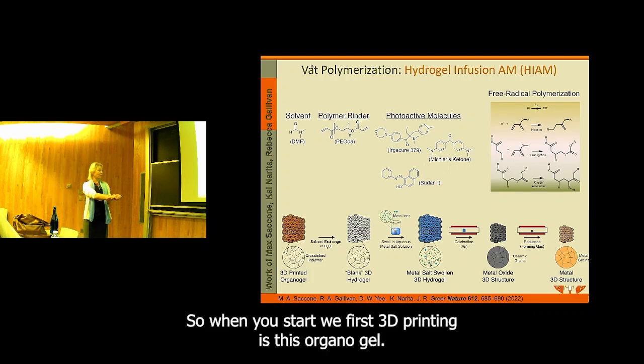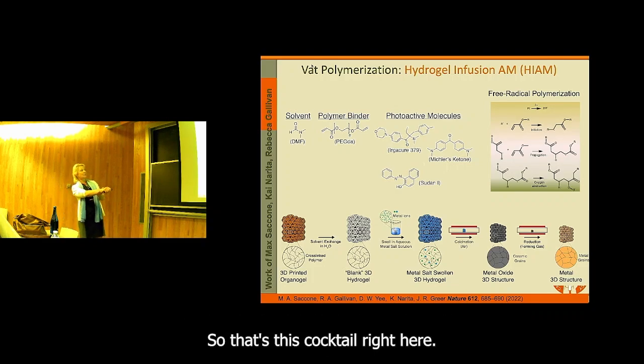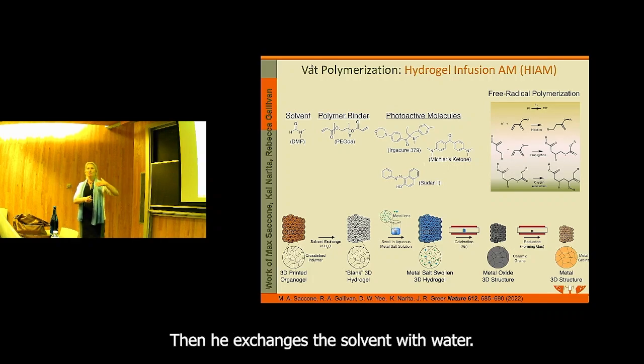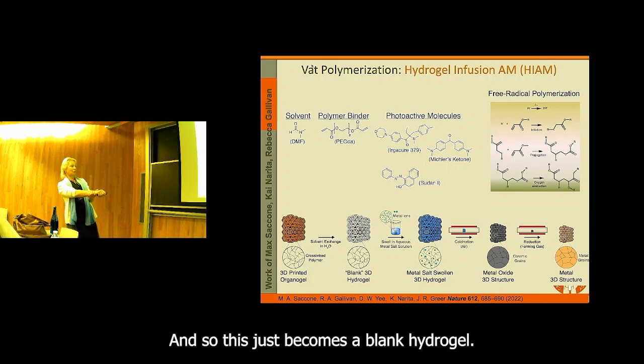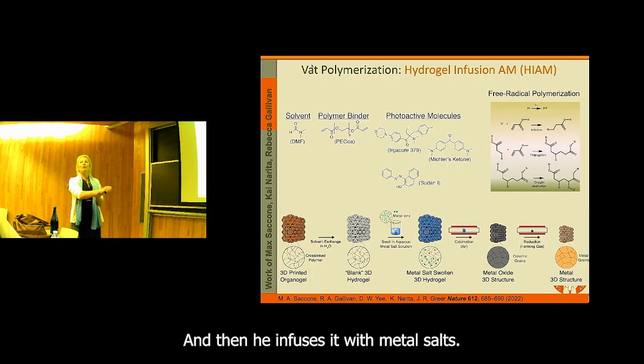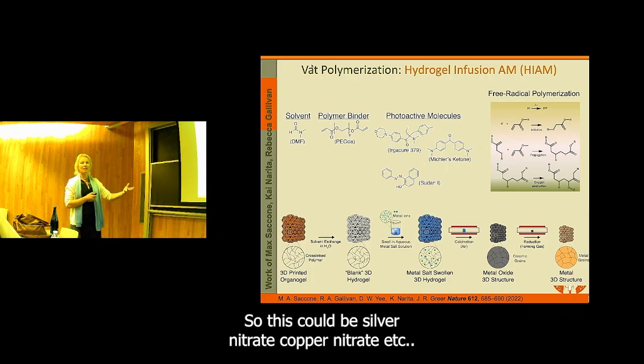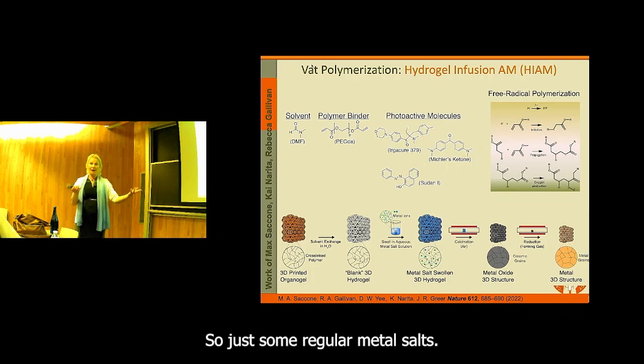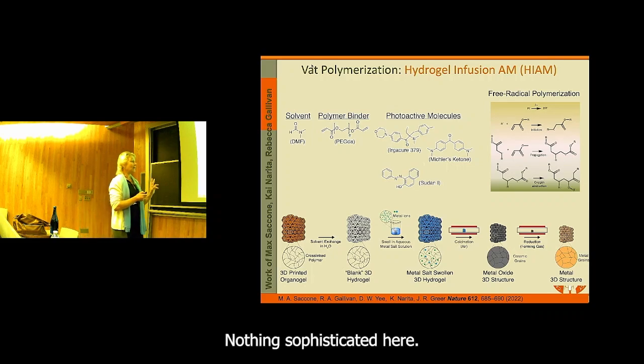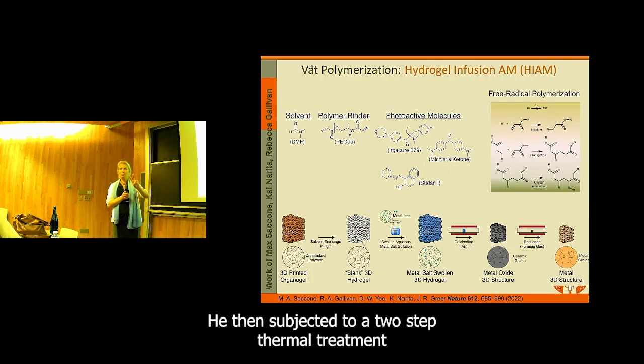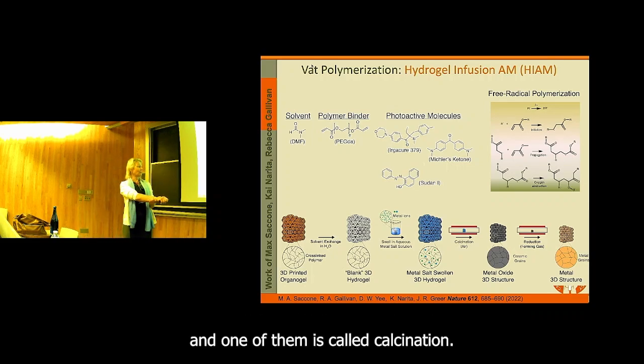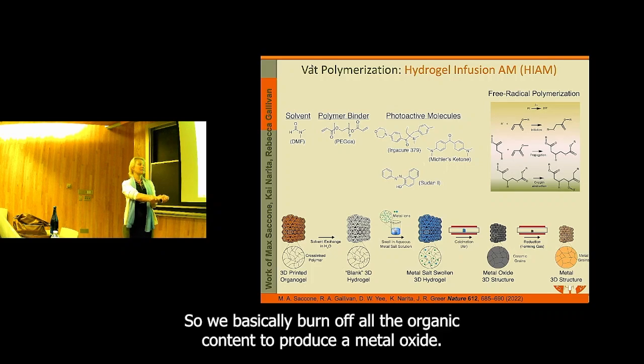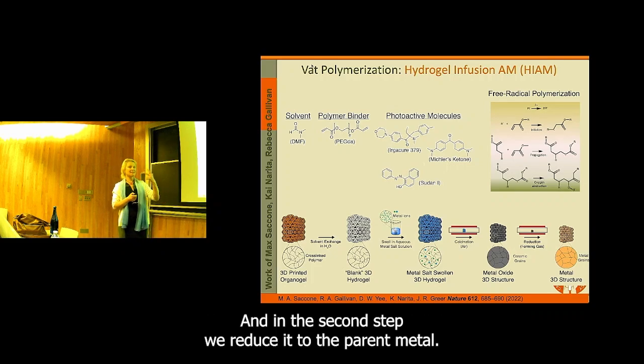So when you start, we first 3D print this organogel, so that's this cocktail right here. Then he exchanges the solvent with water, and so this just becomes a blank hydrogel, and then he infuses it with metal salts. So this could be silver nitrate, copper nitrate, et cetera. So just some regular metal salts, nothing sophisticated here. He then subjects it to a two-step thermal treatment. In one of them, it's called calcination. So we basically burn off all the organic content to produce a metal oxide. And in the second step, we reduce it to the parent metal.